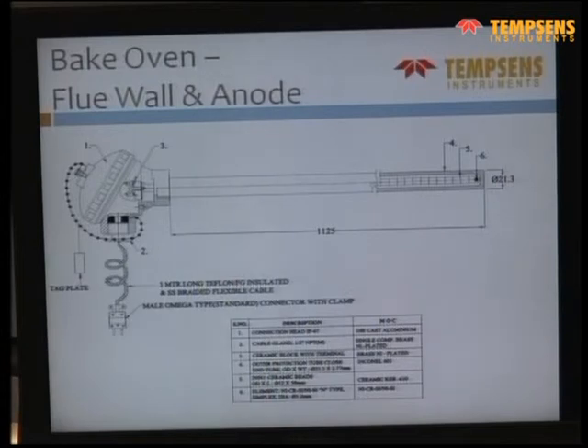Actually suddenly we got a complaint from Bosch that your thermocouples were working and now it is having a drift of 40 degrees centigrade within 1 week's time. So we were also shocked. Everything is the same thing. This was 5-6 years back, and we had no real explanation. We sent them the replacement, and again the same complaint came. So we asked for the samples, and we also studied. It was because of lack of oxygen and the K-type element, one of the elements was getting corroded, and this drifted within a few hours by 40 degrees centigrade. Finally we gave them a sample with inconel sheathing, and inside was N-type element, and the problem was solved. I think it was MI cable we gave, and the problem was solved. So it was a good learning experience for us.